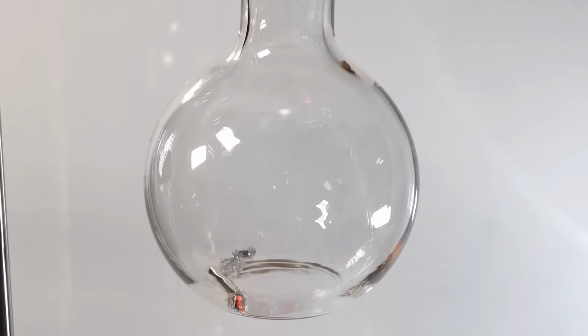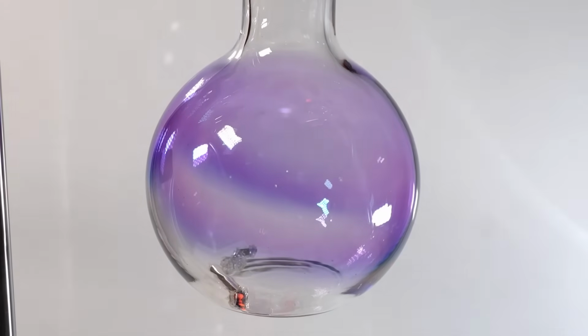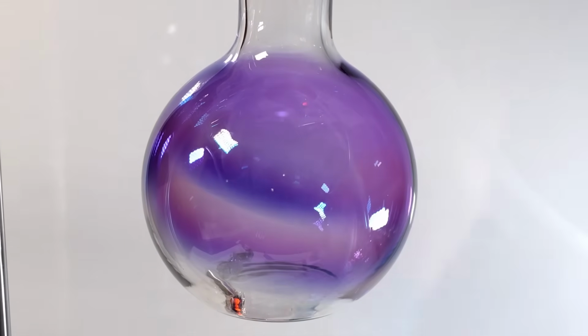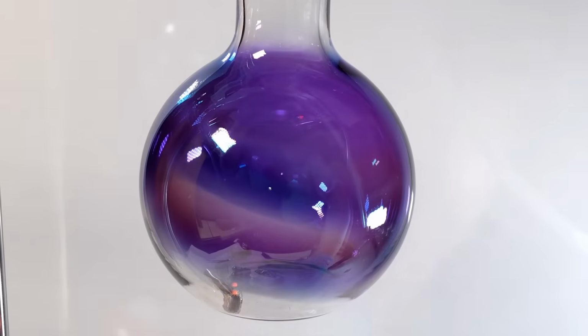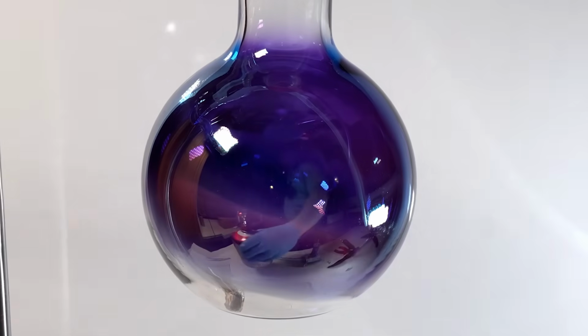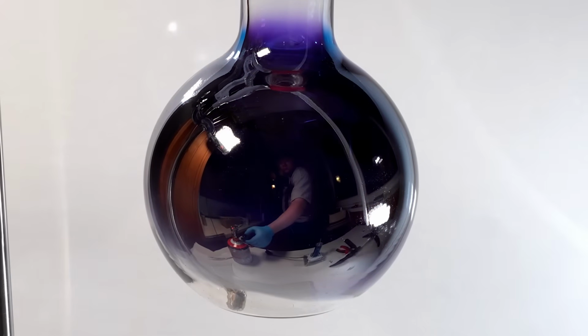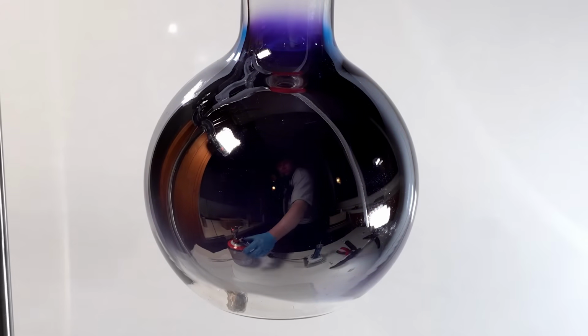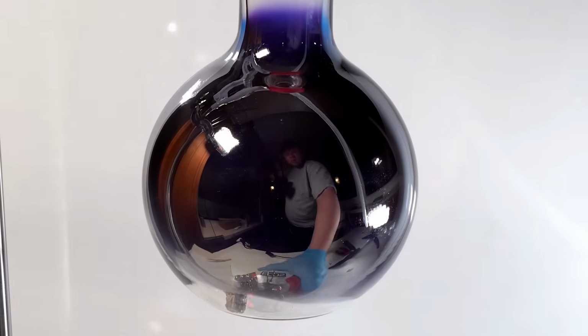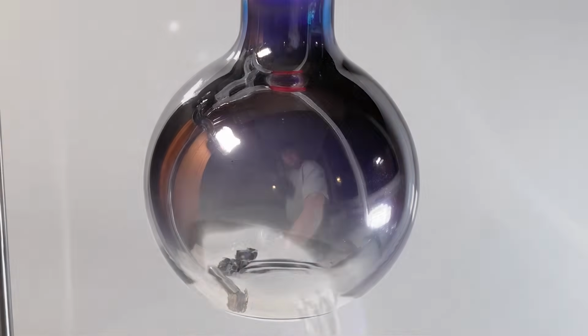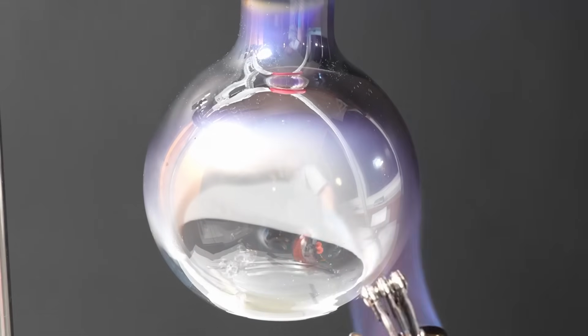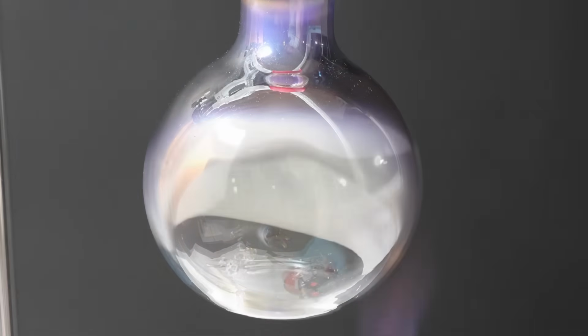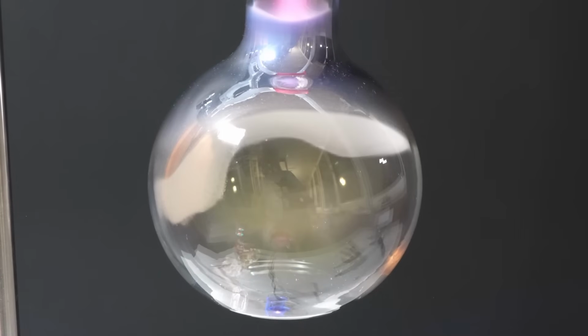Next, as usual, I pumped the air out of the flask and then gradually heated it with a gas burner. In this case, potassium evaporated more slowly than sodium, and it filled the flask with a beautiful metal vapor of a blue-violet color, unlike the brown vapor of sodium. These vapors immediately settled on the glass, forming a shiny potassium mirror. Without wasting any time, I started heating the front part of the flask, creating a window in this mirror. After that, I turned on the Tesla coil and brought it close to the flask.